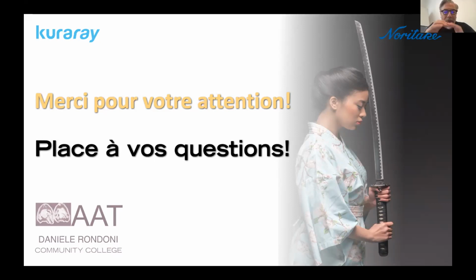This ring is interesting because we can check perfectly whether your furnace corresponds to your programmed temperature, because we all know 1500 specifically for HT, 1550 ideal for cubic, ST and T. But it is important: just by changing the program by 50 degrees, you obtain maybe more translucency or less translucency. But most of all, for example, with HT, if you have a wrong temperature, for example 1550 for HT, your zirconia changes totally because the crystals of the zirconia change dimension, and probably the HTML gains a bit of translucency, but loses a lot of strength.